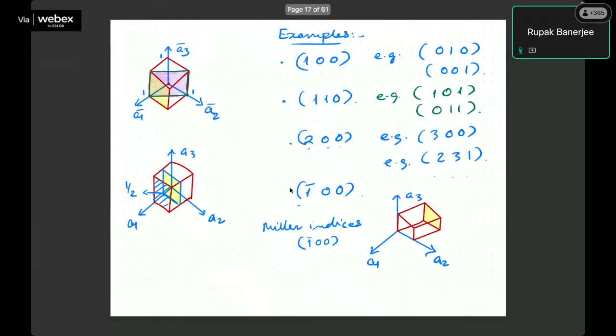Okay, and this is very important because it is conceptually important to understand what the planes are and how you define these planes. And if you are given some kind of a blank crystal system, you should be able to identify that. It is very crucial to understand what planes you are actually reflecting or diffracting when you are looking at diffraction patterns or other patterns, right? For instance, say 100, right? So 100 typically is this yellow shaded plane that I have in here. 100, it is intercepting a1 at one point, and 0 0, which means that it has no intercept along a3 and a2, which means it is parallel to this a3 a2 plane, right? So the plane that is highlighted in yellow is the 100.